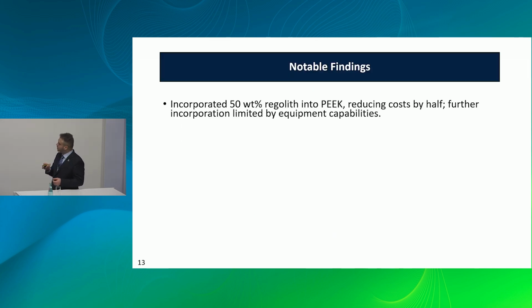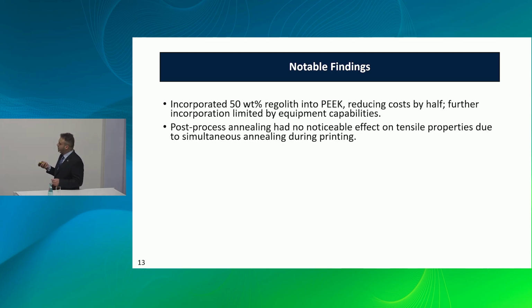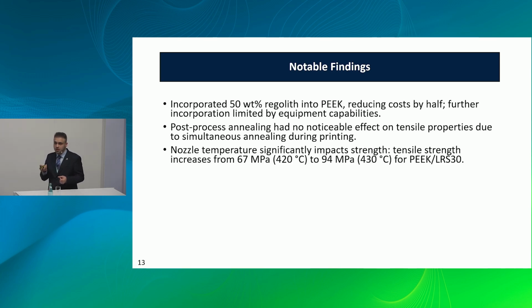Notable findings include incorporation of 50%, which means reducing cost by half, and we can achieve higher, but our equipment is not capable of that for now. And post-processing annealing had no noticeable effect on the tensile properties due to the simultaneous annealing during the printing. And nozzle temperature significantly impacts the strength. Tensile strength increases from 67 megapascals to 94 megapascals by increasing the nozzle temperature by 10 degrees for PEEK and